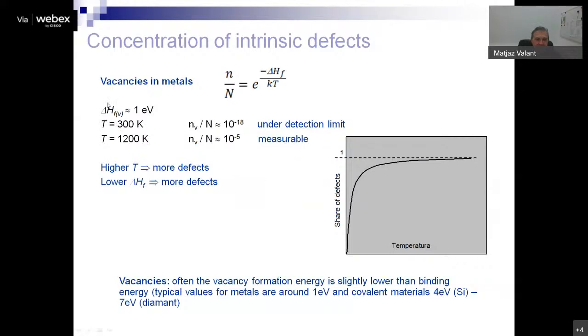Now, the formation energy for a vacancy in a metal is around 1 electron volt. So this is this particular term here. Then we can easily calculate that at about room temperature, we have 10 to minus 18 share of defects in the crystal. That is still very, very low, and actually we can't really detect this small number. But if we heat up, let's say, an iron slab, then we will increase the share of the defects to 10 to minus 5. And that is already high, and it's already measurable.